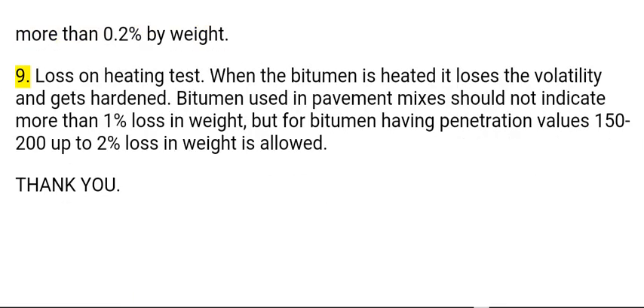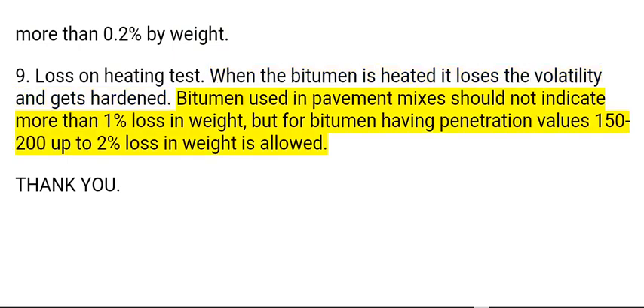9. Loss on heating test. When bitumen is heated it loses volatility and gets hardened. Bitumen used in pavement mixes should not indicate more than 1% loss in weight, but for bitumen having penetration values 150 to 200, up to 2% loss in weight is allowed.